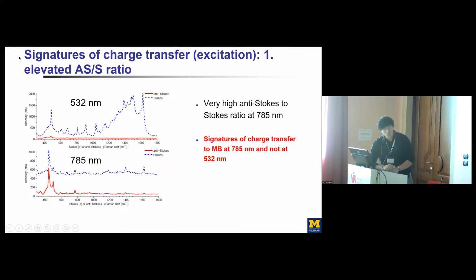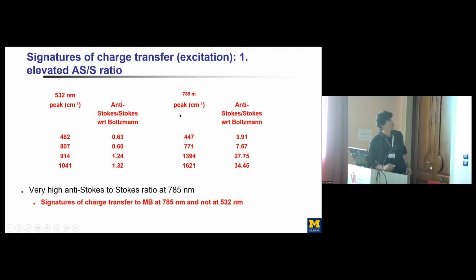So we can even be more quantitative about this. Here I've basically selected a few vibrational modes of this methylene blue molecule, and we have measured anti-Stokes and Stokes and compared them to the Boltzmann distribution. And what you see at 532, basically the molecule is not heated. It's kind of sitting at the temperature of the nanoparticle itself. On the other hand, when you go to 785, you see that this ratio of anti-Stokes to Stokes versus Boltzmann is quite high, meaning that this molecule is getting hot.